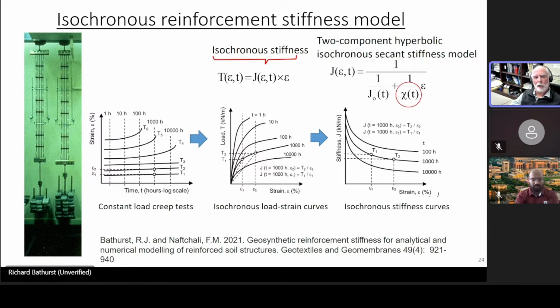And this parameter, actually it's chi, was most responsible for capturing the creepiness, if you like, of these reinforcement materials. So if this value is very, very high, approaching infinity, then basically our reinforcement is linear elastic. But as it becomes more load and strain dependent, then this value becomes smaller and smaller.